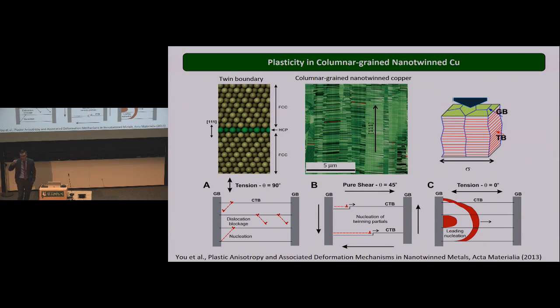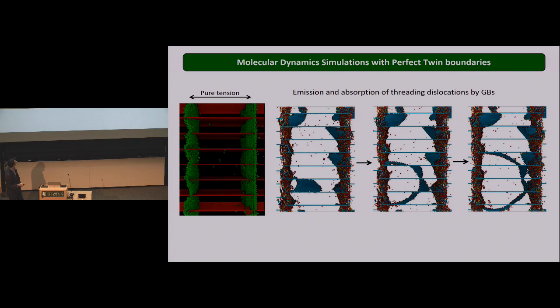The threading dislocation just goes through the material, all right? So we took this approach and looked at it first with molecular dynamics simulations. In the case of a threading partial, what I want to show here is that these dislocations nucleate, travel through the grain, and disappear on the other side.